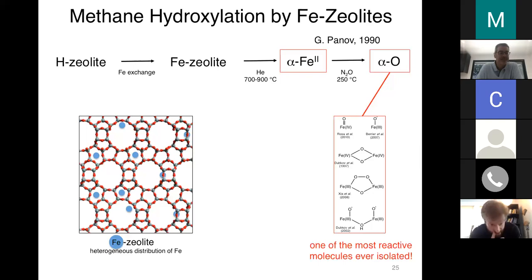But it turns out studying metal sites in zeolites is very challenging because you have this heterogeneous distribution of metal sites. And it ends up being very challenging to take these systems and study them spectroscopically and understand what spectroscopic signals are coming from your sites of interest versus these so-called spectator sites that don't contribute to reactivity. And because of these challenges, many of which went unrecognized, there's a huge amount of speculation over the nature of the alpha oxygen site, largely because there were no reliable experimental data that would have provided insight into this species.